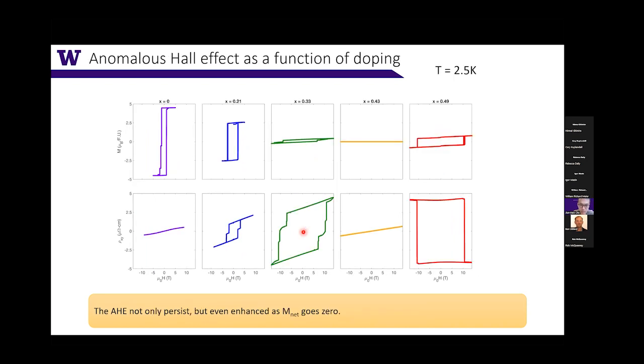Similar things can be seen in the doping. As a function of doping, you can also see that the anomalous Hall persists even when the magnetization vanishes. Here in this yellow curve the magnetization vanishes just because the coercive field is too large, so we cannot see the flipping of rho xy, but if you field cool, you can actually see the anomalous Hall, and it remains comparable to the neighboring dopants. What is quite interesting is that the anomalous Hall resistivity actually grows when you go to higher doping.